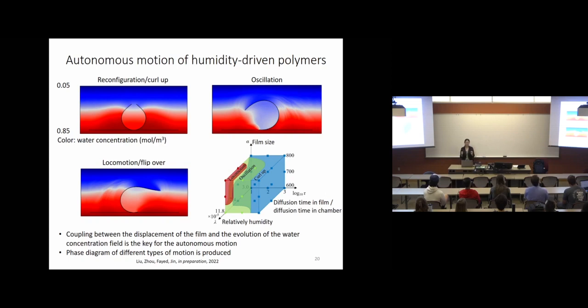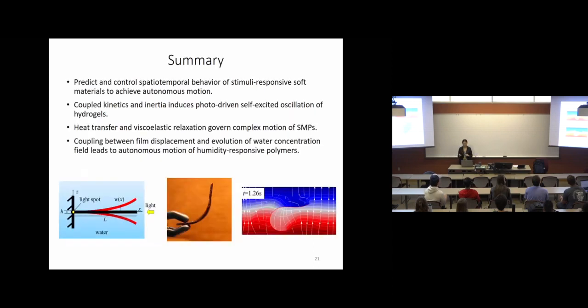But the key point we learn is that it's really this coupling effect. First of all, you are deforming the film to different positions in the chamber. But on the other hand, the film is sort of impermeable. It can also move the liquid around. Therefore, this coupling effect gives rise to this very interesting and complex autonomous motion. So to summarize this first part, we show that indeed we are able to predict and control those spatial temporal behaviors of stimuli-responsive material. We show this coupling of kinetics and inertia can induce photo-driven self-excited oscillation, and heat transfer and viscoelastic relaxation govern the complex motion of shape memory polymers. And the coupling between film displacement and evolution of water concentration leads to autonomous motion of humidity-responsive polymers.